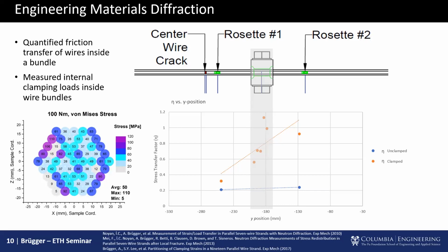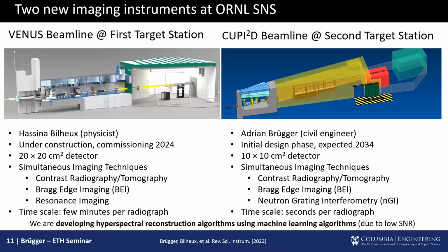So here, what we actually posited in the end is that this is a function of the diameter compatibility or incompatibility of the wires, because the wires have about 15 microns of tolerance in production, and that is sufficient in this relatively tight packing regime to actually cause this huge chaotic behavior. So this is now a problem, because now we are looking at a stochastic field instead of a prescribed mean field distribution, where we say, well, this cable, we can assume this is the compaction, but it's truly not that simple. So this is how I came to neutron scattering.